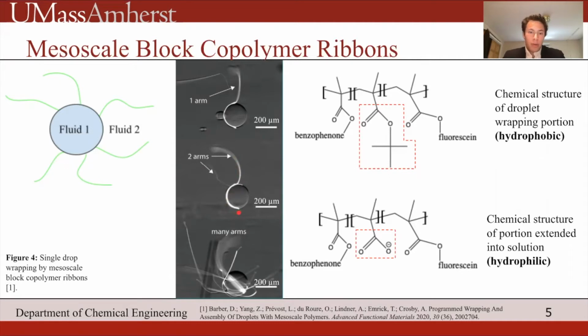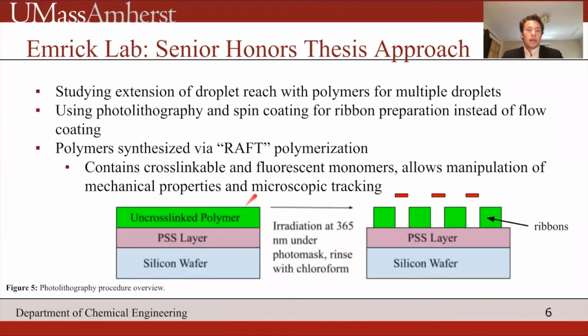However, there were two drawbacks to this paper. The first one was that the polymers were prepared using flow coating, which is not a scalable process. And the second was that this only studied interaction with a single droplet. And so the purpose of my thesis, which I'm working on with Dr. Zifei Yang, is to study the extension of droplet reach with polymers for multiple droplets using photolithography and spin coating for ribbon preparation instead of flow coating, which allows us to scale up to a much larger degree.